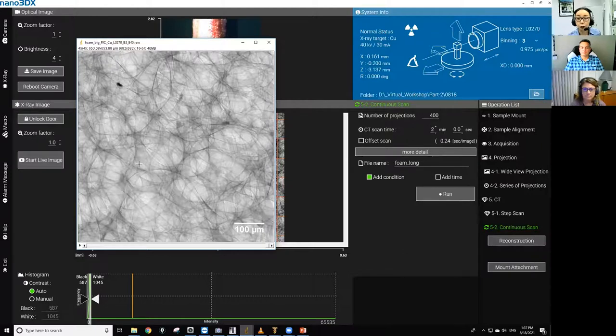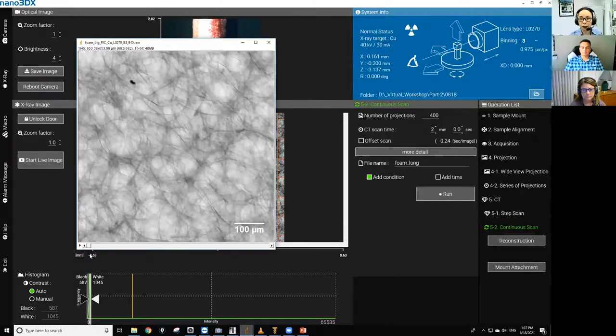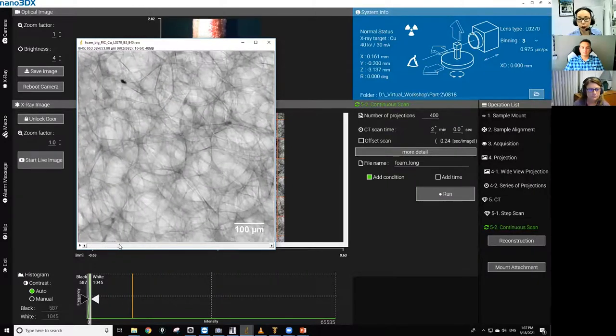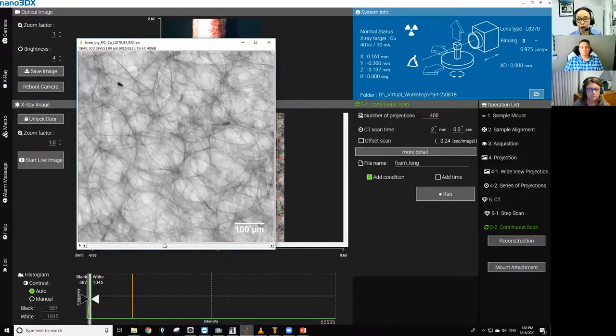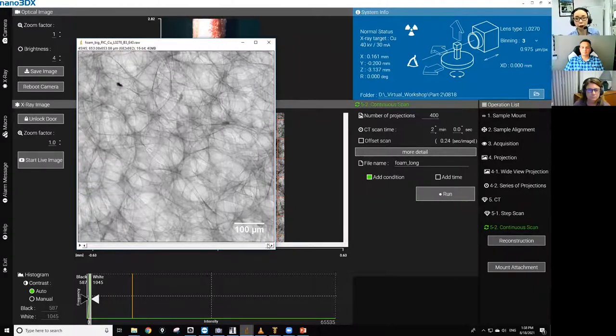So this is a 2D projection from the foam we just scanned. At the top, you see 45, so this is after 45 minutes. Now let's rewind this all the way to the first minute. This is the first minute mark projection. When you go through from 1 to 45, you can see that this foam is springing back. It's still moving for the first almost 30 minutes; this is 22 minutes, and this is 30 minutes. After the 30 minute mark, the movement is very small. From those projections, after 45 minutes, you can comfortably say that the sample gets settled and stops moving after 45 minutes.